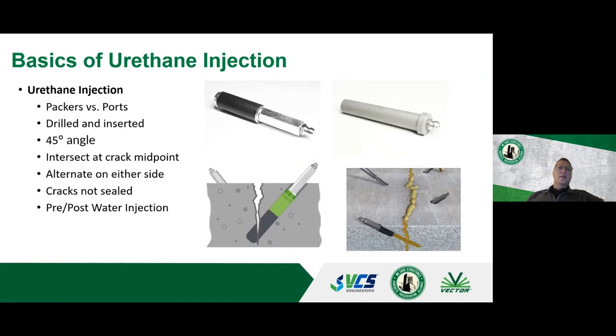Urethanes are done differently. In epoxy injection, you use ports. In urethanes, you're using a packer. And so you're drilling in and you're trying to intersect that crack at the midway point through its thickness. And I think the drawings illustrate this very well.